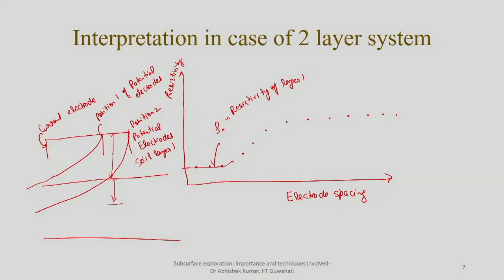Now what will happen after this, it is gradually changing. Why it is changing? Because now your electrode spacing is such that your potential electrode is far distance from the source or from the current electrode, such that it is able to detect the equipotential line, or the characteristic of equipotential line or the potential drop, which is dominated by second layer, but still there is a significant portion of equipotential line which is coming from first layer. So, this is some kind of transition, you can call it as transition in resistivity between layer 1 and layer 2.